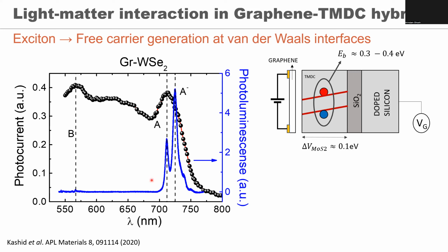Nice, thanks. So you see, there's something important here. The important thing is, if you see the photoluminescence, the green or the blue one of the chalcogenide layer, which is WSe2 in this case, the photocurrent measured in the graphene essentially starts for all energies of the photon higher than the optical band gap, that is, the A exciton is where the optical band gap starts.